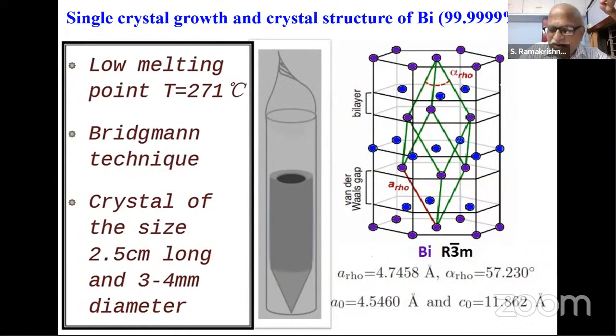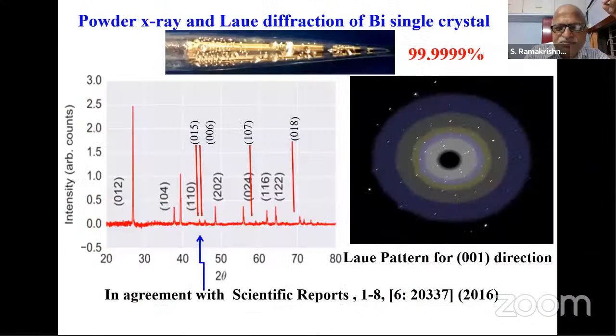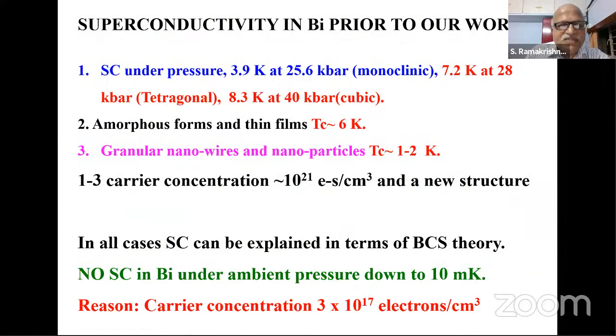It has a rhombohedral structure, as I said. Its unit cell is rhombohedral with 4.75 angstrom, and it is a distorted rhombohedral structure. I told you this distortion is coming from the Peierls-like distortion in the system. You can do X-ray diffraction to confirm its structure, and check the quality of the crystal by X-ray backscattering measurements.